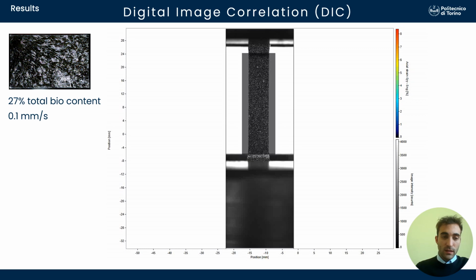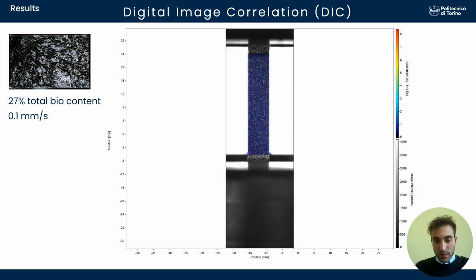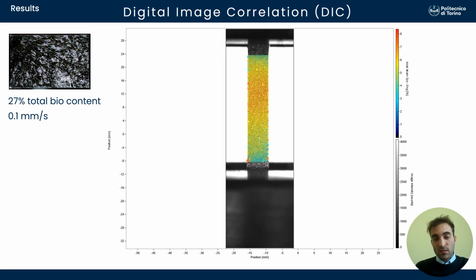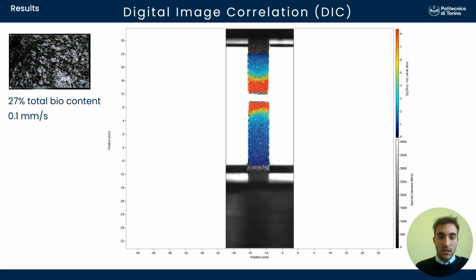In fact, in the case of the specimen characterized by the 27% of total bio content tested in quasi-static condition, we can see from the digital image correlation images that there is a concentration of the strain in a particular zone of the area of interest, which is also the zone where the failure happened.